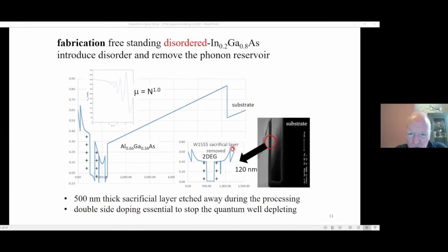If it's removed, the actual electronic system looks something like this. We've got a free surface here. We've got band bending due to charge. We've got the fixed positive charges in the lattice that the electron gas sees. We've also got this new free surface here that we've etched away. That's this surface down here. So what does it look like when we've etched it away? It looks like this. This is 120 nanometers thick. They still conduct, just about.